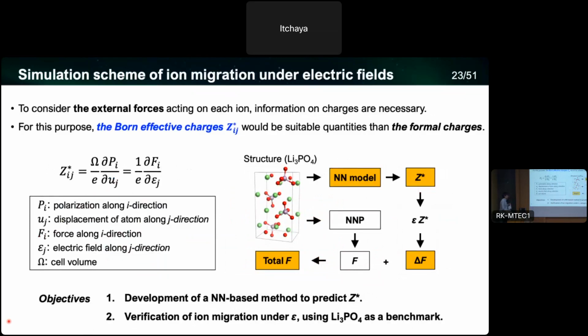Then, if we try to investigate the ion migration under the electric field, first we need to consider the external forces acting on each ion. To get these external forces, we need the information of the charges. A simple way is just to use the formal charges, like for oxygen we can assign -2, and for lithium we can assign +1. But we think that those charges should be variable and change depending on the local atomic environment.